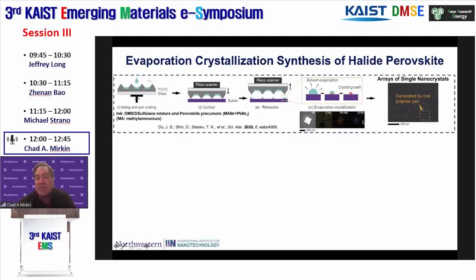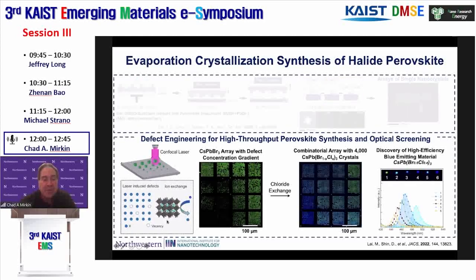And so over here to the right, you can see arrays of literally millions of single nanocrystals made in this particular manner. Now, those are all the same, at least if we use all the same precursors. And there are a variety of different tricks you can use to now begin to turn a library of the same materials into a library of different materials. And one way to do that is to use a laser to induce ion exchange. In this case, we're affecting chloride to bromide exchange and now changing the ratio of chloride and bromide in the resulting structures. And you can do this with a really fine degree of control.